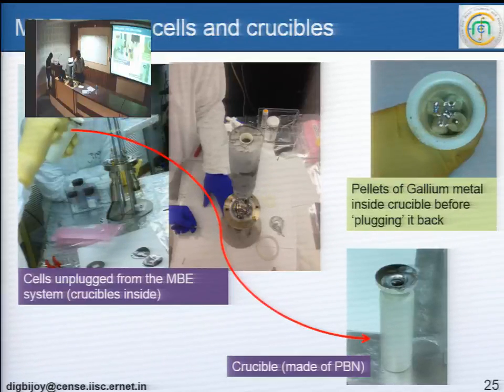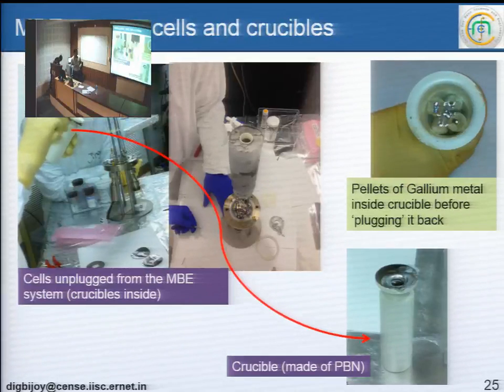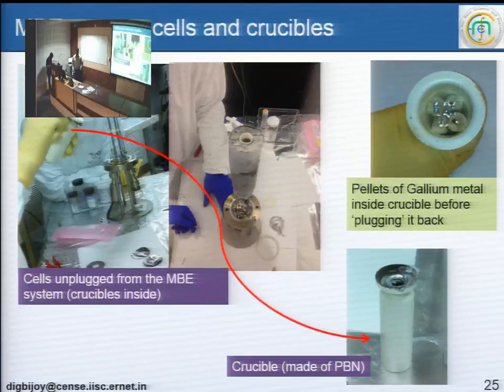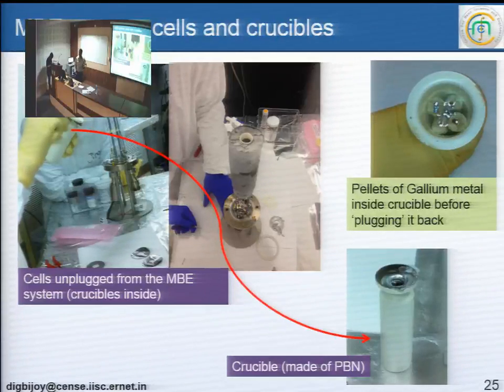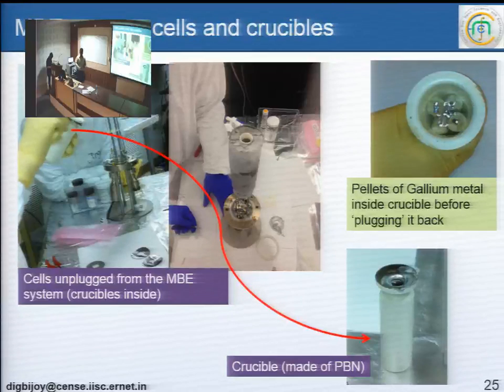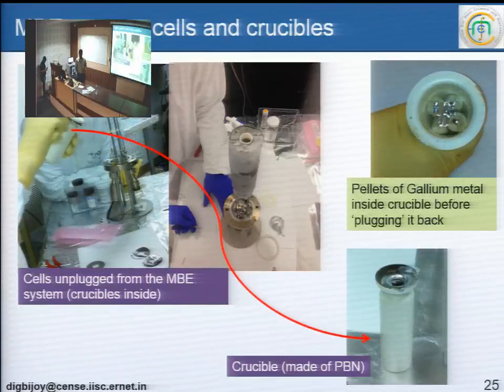And then to get this done, you have to open the system, right? You have to break the vacuum, take it out, because the vacuum inside is very high. So you cannot just break the vacuum. Say you have 760 torr outside here and you have 10 to the power minus 11 torr inside, which is 10 to the power 13 times lower pressure, right? You cannot just open the chamber like that. It will be a bang, because there is a huge difference in pressure. So you have to go step by step, and even opening the system takes maybe days or weeks.